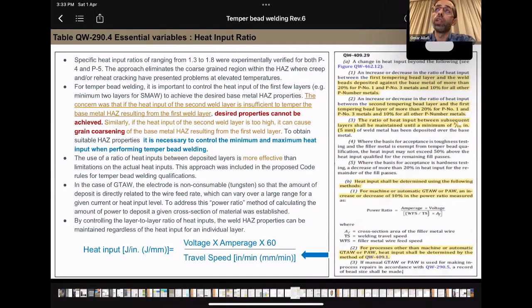Why? Because in SMAW, you're using an electrode, and this is getting molten and deposited as a weld. So there is a direct relationship between the current and the weld deposit. But in the case of GTAW, the electrode is non-consumable, which is tungsten. So the amount of deposited weld can vary over a large range of given current or heat input level. So to address this, a new terminology was developed, which is the power ratio.